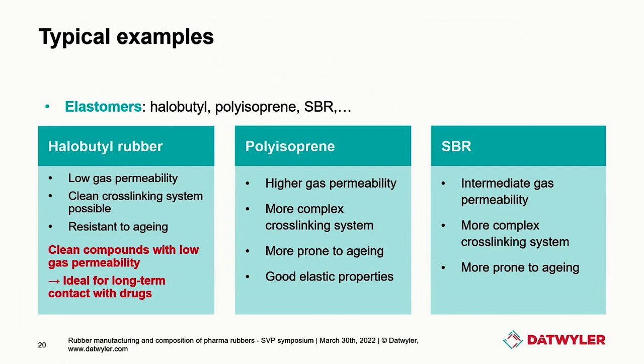And also this one is more prone to aging, which means that you will need to add more antioxidants, for example. But on the other hand, polyisoprene has some very good elastic properties, which is why it's used nevertheless for some applications that really need this. And then a third example was SBR. This one has an intermediate gas permeability, so intermediate between halobutyl and polyisoprene. But also this one has a more complex cross-linking system and is also more prone to aging compared to halobutyl rubber.